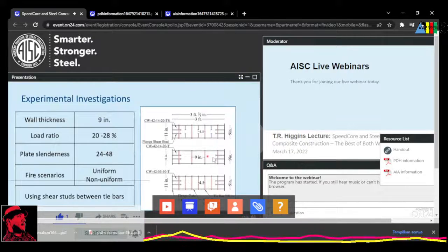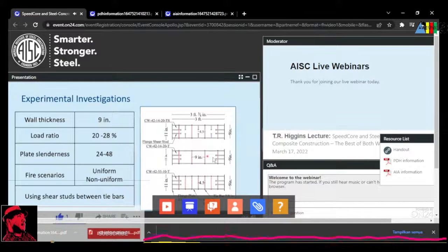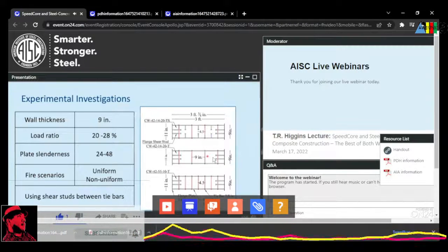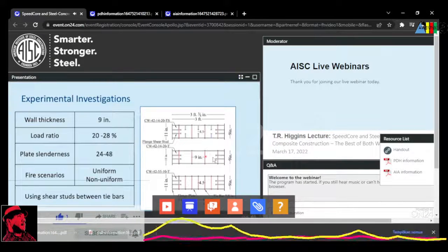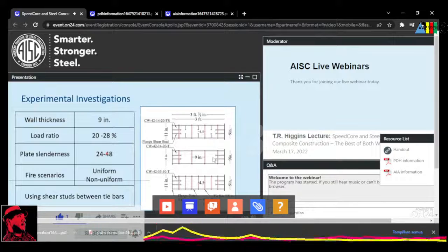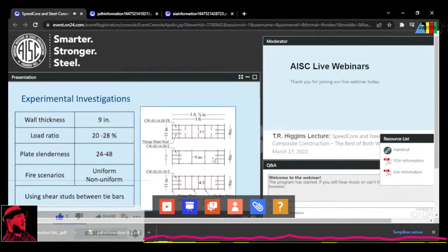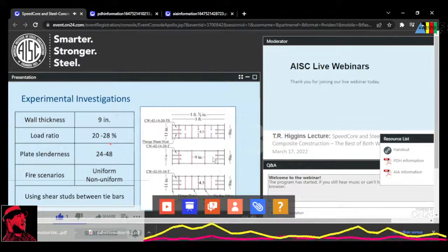We conducted our experimental investigations on the same wall specimens we had used earlier in Module 3 of this presentation for cyclic testing. Since the failure in those tests was localized at the base, we were able to reuse the remaining length of the specimen for fire testing. Specimens were 9-inch thick with 3/16-inch thick steel plates, slenderness ratios of 24 and 48. Both uniform and non-uniform heating were included. The actual load levels in the tests were about 20 to 30% of the wall concrete strength.